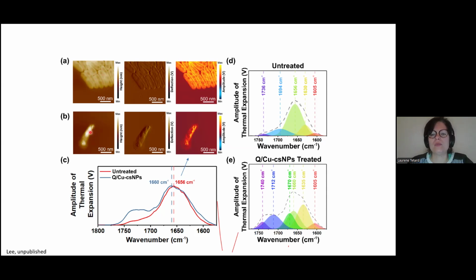And then we could place the tip at different positions on the bacteria and collect their infrared signature. So that's what we did here. The blue one is on the treated cell and the red one is on the untreated cell. So we see that there's a clear difference in this range for the amide 1 and amide 2 signature of the bacteria. And unfortunately, at the time, our system only had a limited range of infrared illumination. Since then, we've expanded our range of measurements, so we can now get infrared spectra from 800 wave number to 1800 wave number. And so we can get more information about the chemistry of the cell.